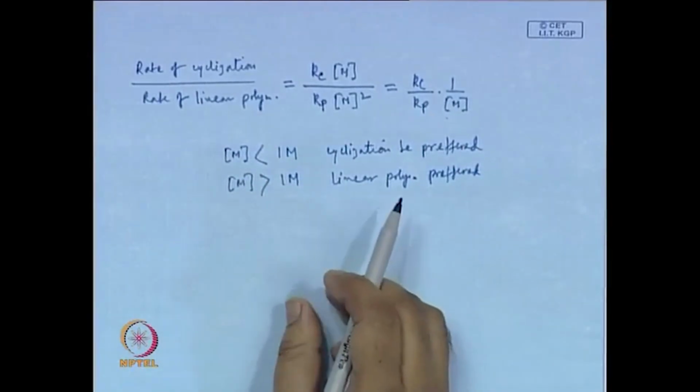So, it is always advisable, to minimize cyclization, to use the maximum possible concentration of the monomers. The best we can do is a bulk polymerization, where we carry out the reaction with the monomers and the catalyst, if required. That is the maximum possible concentration you can have to minimize the cyclization.